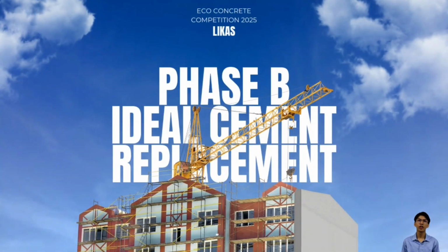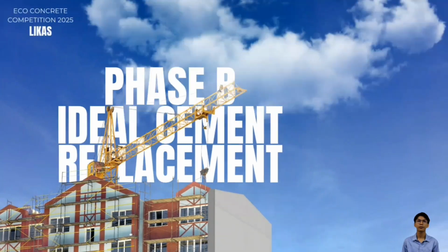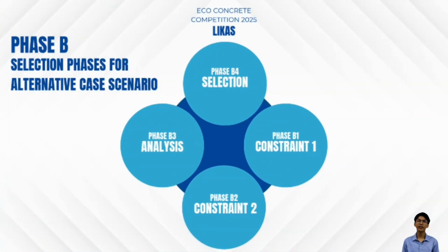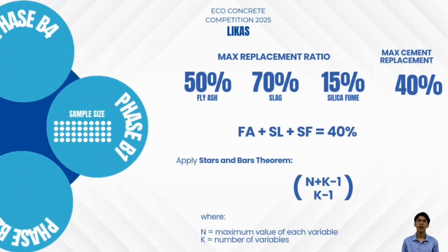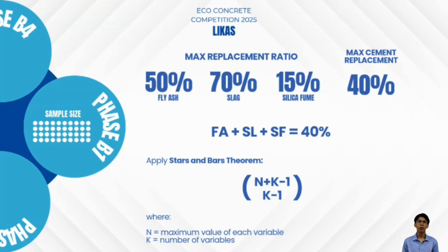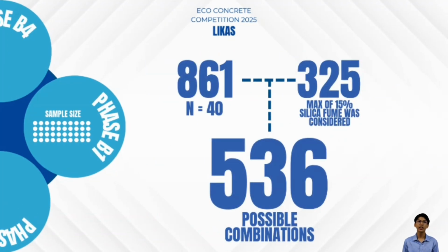We now move to phase B, where we idealize the fly ash, slag, and silica fume ratio relative to cement content. The selection of the ideal ratio will be further divided into 4 phases. By applying the stars and bars theory, where we determine the number of non-negative integer solutions to an equation, given by the formula shown, we can determine the possible number of combinations. When n is equal to 40, the number of possible combinations is 861.